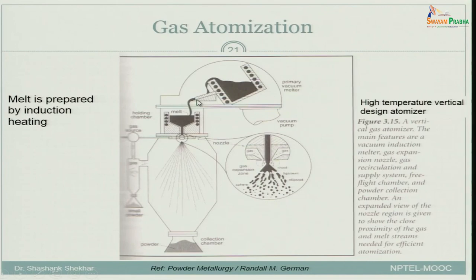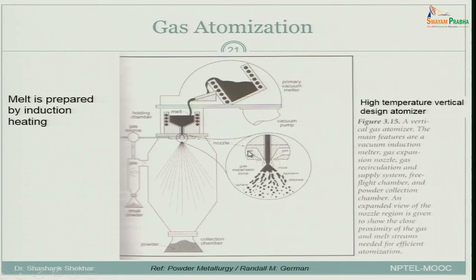Because of the energy of the gas, the liquid stream gets disintegrated into very small ligaments. There are stages of formation: it first forms ligaments, then ellipsoids, then flakes, and finally spherical particles. The powder particles should lose heat and freeze before they reach the boundary of the cylinder — if they hit the wall before freezing, they will be squeezed into a flat shape rather than the desired spherical shape. Spherical particulates have advantages: good flowability, good compactability, and high compressibility.